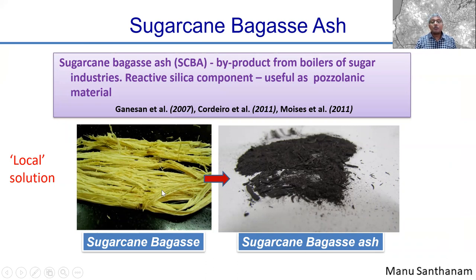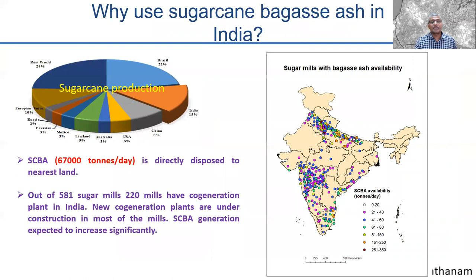Okay. So what has been looked at in research previously has clearly shown that the finer powder that you get at the bagasse seems to have very high quality silica available. And this silica is in the amorphous form, and that can lead to good reactivity in the cementitious matrix, just like fly ash. Okay. So our aim here was to understand what would be the best way to utilize this material. What amount of processing would we need to do? How well do we need to actually further process this material to get the right quality as far as cement replacement is concerned?